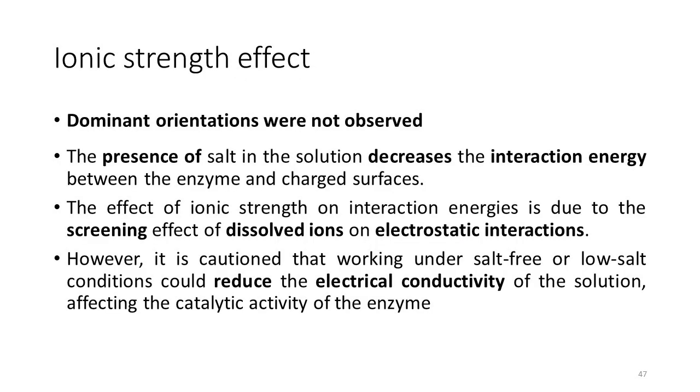Watching the results that I obtained, mainly in the table, I can say that the ionic strength is the experimental variable that most affects the absorption of the protein. Basically, the presence of salts decreases the interaction energy. Probably this is due to the screening effect of the dissolved ions on the electrostatic interactions.